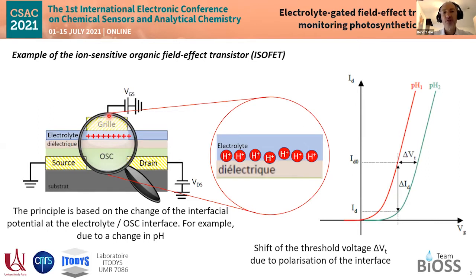the electric field in between the gate and the semiconductor due to the gate voltage is present, but also an electric field or a potential drop due to the accumulation of charges at the interface, typically here at the electrolyte dielectric interface. So for this easy example, due to accumulation of protons at this interface, we can see a change in the transfer curve. When I say change, it's generally a shift of that transfer curve, that is of the gate voltage seen or sensed by the sensor, by the transistor.